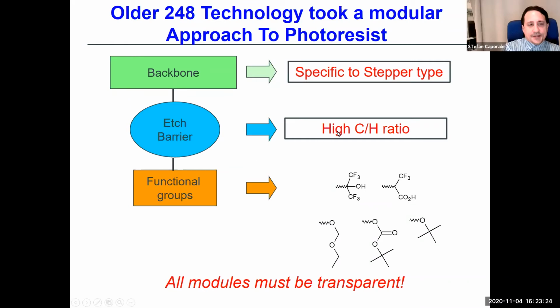And the etch barrier is basically something that has to resist the plasma etch, and that's done by a high carbon to hydrogen ratio. So the more carbon you have and less hydrogen, the etch will rip these hydrogens off and oxidize your carbons, allowing your material to ash away. So you need to have them; cage groups are best for that.